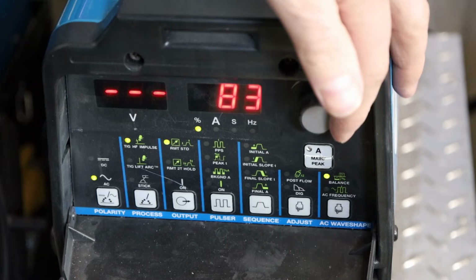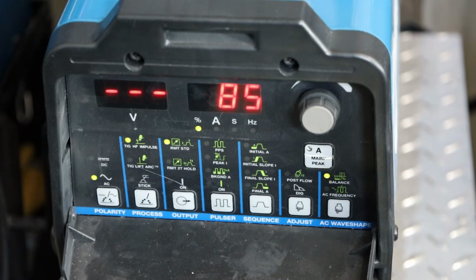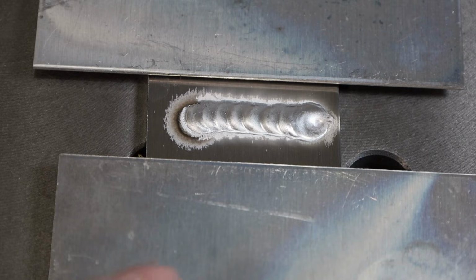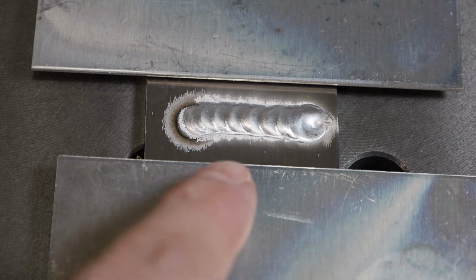Let me demonstrate here just for a minute on this plate. I've turned the balance on this Miller up to 85%, which means 85% of the time is going to be electrode negative, and 15% of the time is going to be electrode positive. And that's not going to give me enough time to effectively etch off that oxide layer. So watch this. You can see it's just making a mess here, right? It's doing okay, but I don't have a nice result at the end because I didn't have enough of that etching side of the cycle to clean the material.